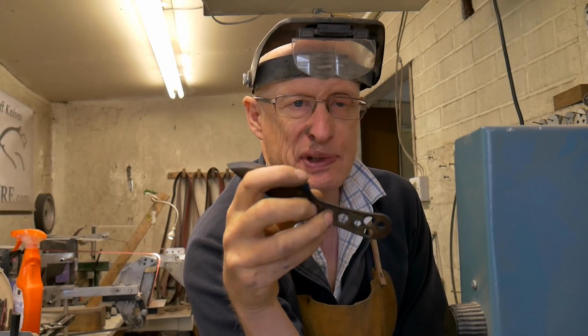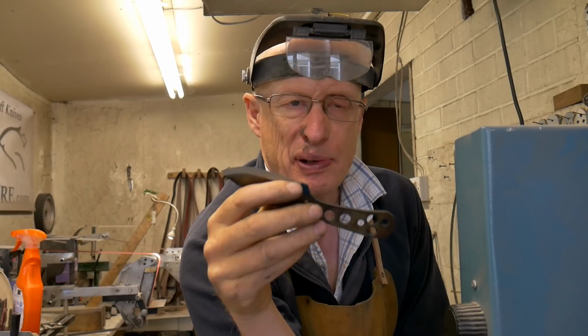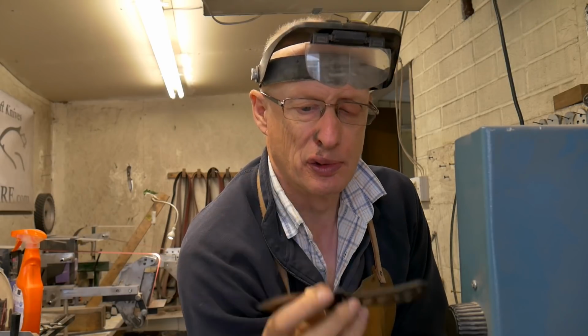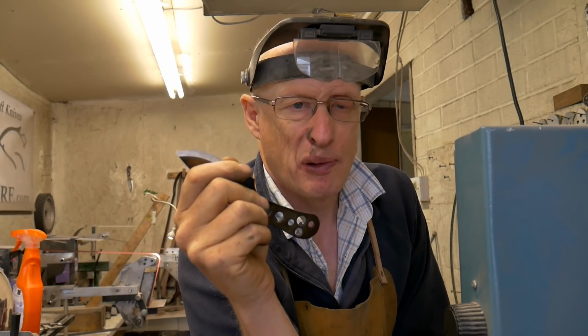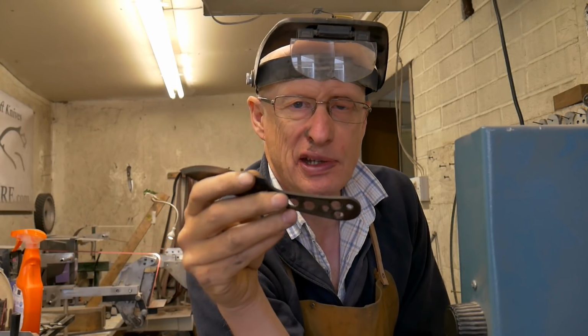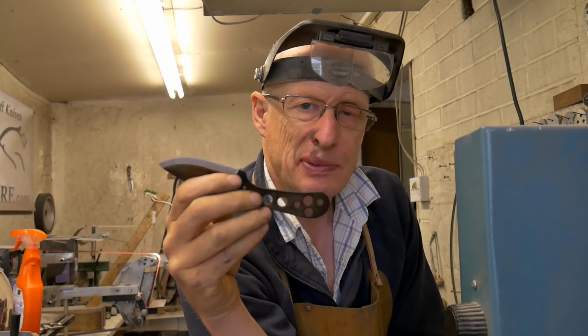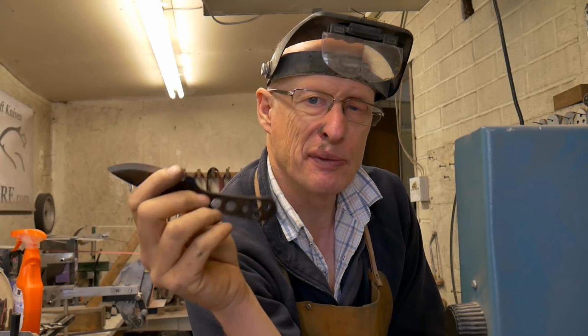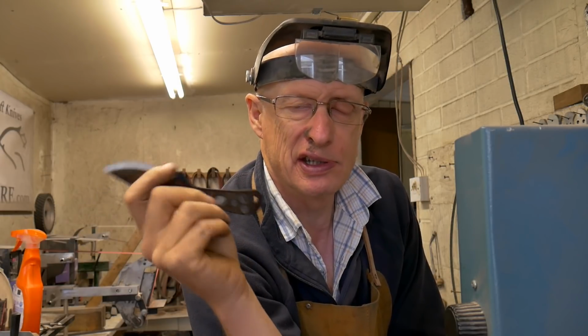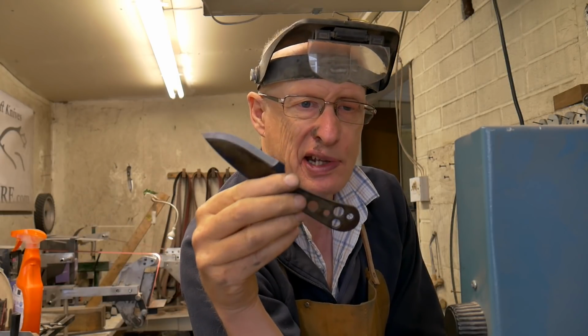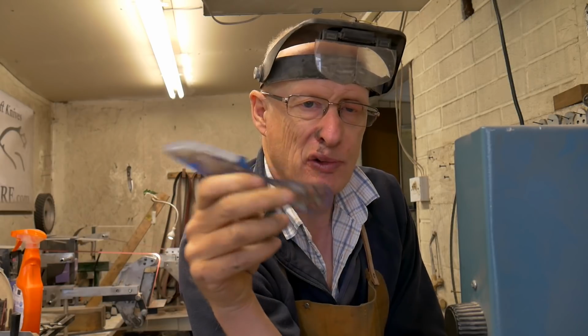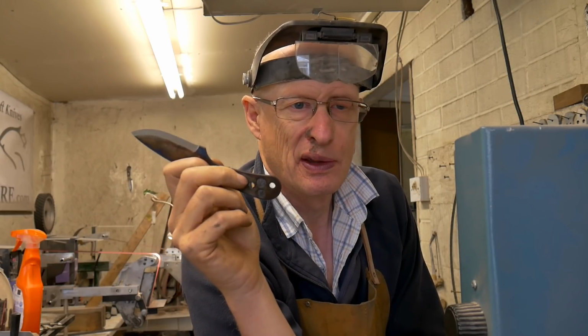If it chips, then we look at the chip, and if the chip is symmetrical, then we can probably be sure that the heat treat is still good, but it just needs to be tempered a bit higher perhaps, so that it will fail to a roll rather than a chip, which is preferable for a Scandinavian grind, because a roll is easier to rectify than a chip.